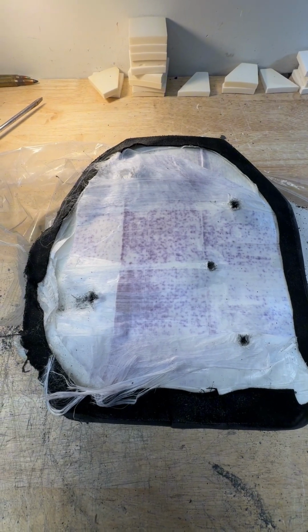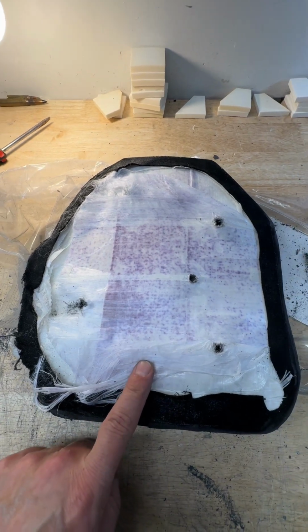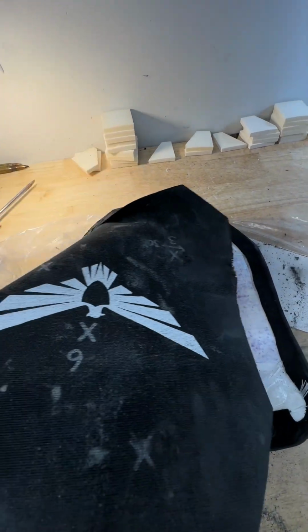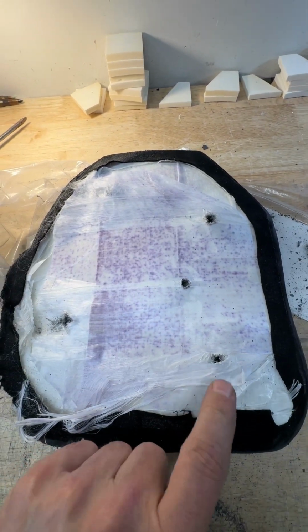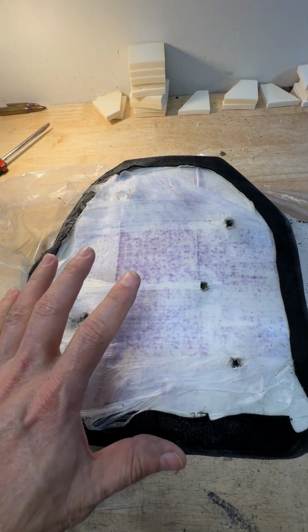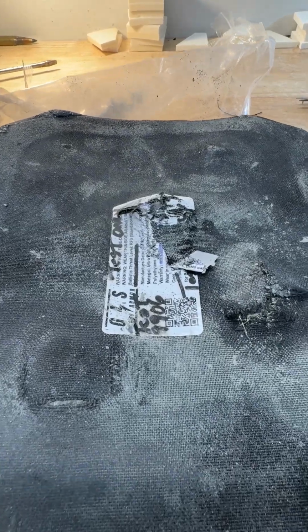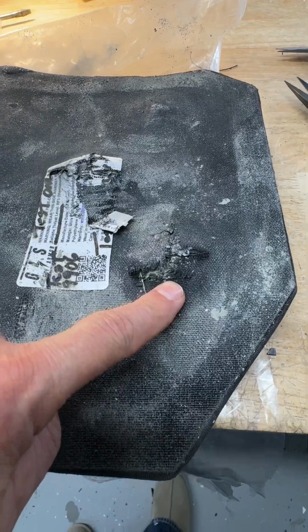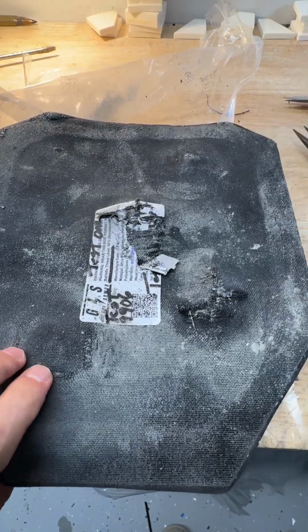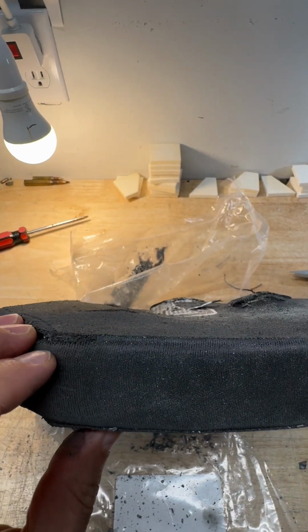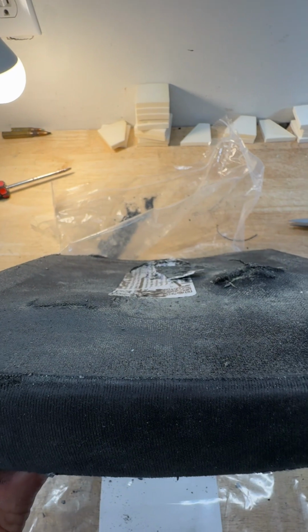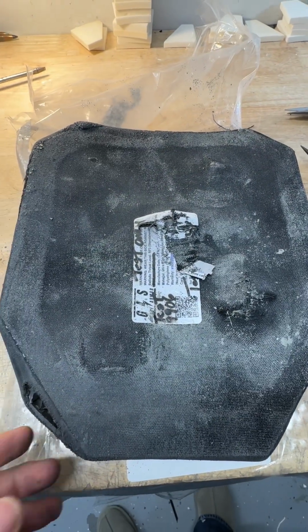Okay, so here is the crack arresting layer with the quarter cover removed. And so this is what you would see underneath the actual cover. This cover was taken off, and this is what you have. So you can see how the entry points for the projectiles are protected, and it helps to protect that solid ceramic strike face here. Okay, so keep in mind we shot this to failure, so we did have a very nice back face deformation in here, and the back face deformation is really not all that noticeable. I think we came in the low 30s, which is not bad for a silicon carbide plate, but the obvious advantage is with the trauma reducing layer that we'll show you in just a minute. But we had a really good result back here. Of course, this plate was shot until it failed, and that test report will be followed on right after this video.